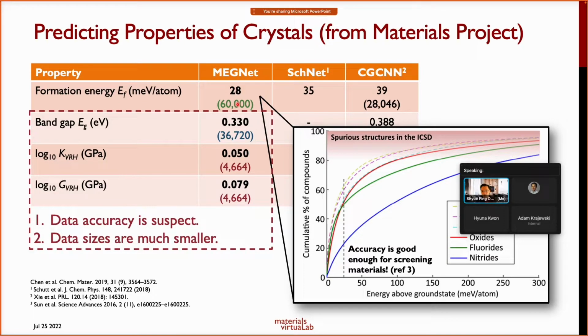Now, you also notice these numbers in brackets. These are basically the number of crystals that were in the data set at the point in time where we actually trained this MEGNet model. So there were about 60,000 crystals in the Materials Project at the time. But what you'll notice again is that the data set for things like, for example, the accurate band gaps is much less, almost about half the data set of the formation energies, and the data set on the Bulk and Shear modulus is even smaller.